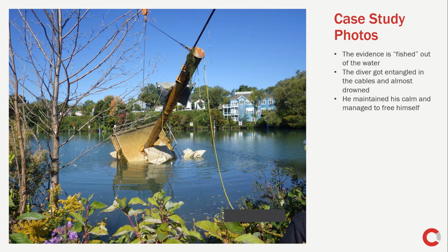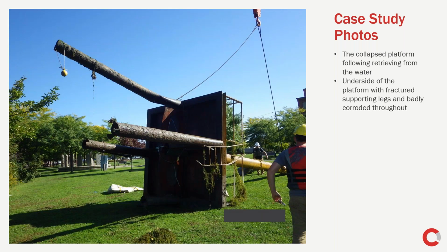The incident occurred in March and we retrieved the platform in September. So the platform remained submerged underwater for several months, a condition which changed its appearance. The platform was brought ashore and we looked at it. It has 4 legs and you can see 2 of them were severed. One was bent and mechanically deformed, and the 4th one is in the shadow and it's not visible, but it was damaged as well. Because it was staying submerged underwater for such an extended period of time, the structure was covered in algae and mussels.